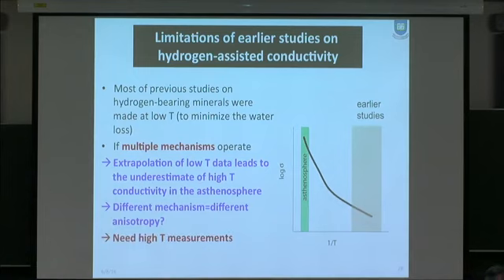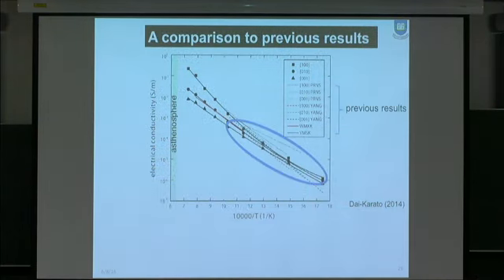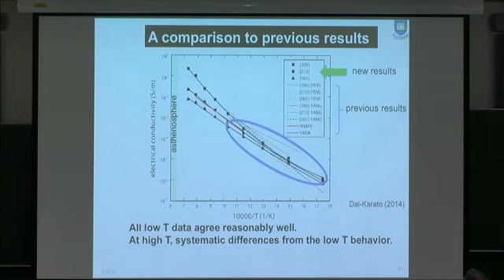So therefore, you need high temperature measurements of the electrical conductivity. We spent some time in my lab doing new measurements at much higher temperature conditions with some technical developments, and those results are compared in this diagram. All the data are here in the low temperature range. They agree more or less within the uncertainties. But in addition to covering the temperature range covered by all the studies, we also conducted experiments at much higher temperatures. Then you can see quite clear evidence that at high temperatures, trends are quite different in two ways.